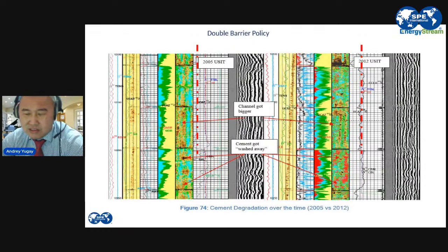So what I'm trying to say is that, yes, it might be that at surface the leak rate is low, but if the outer casing, in our case 13 and 3/8, for example, gets corroded somewhere in the middle of the well across aquifers or other permeable formations, the leak rate will be much higher than what you measure at surface. So this is something you need to consider as well. So why am I talking so much about corrosion and cement degradation? Because it's part of our cement barrier, our secondary barrier, let's say. Because you understand, if the cement gets degraded, it cannot be empty. There is something in between the cement and carbon steel. Our casing is still carbon steel. So that might be a corrosive environment, and that supports the corrosion of our secondary barrier, internally, externally.